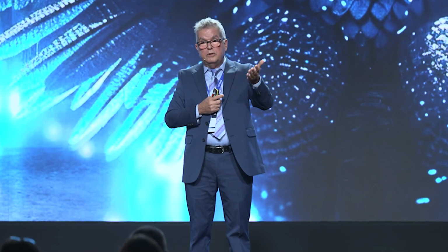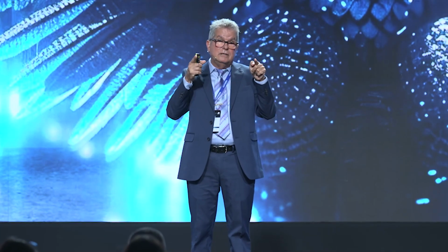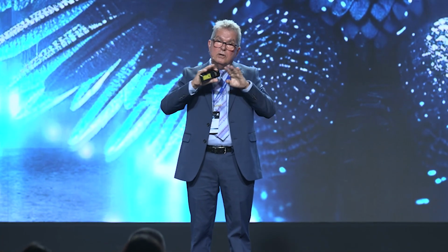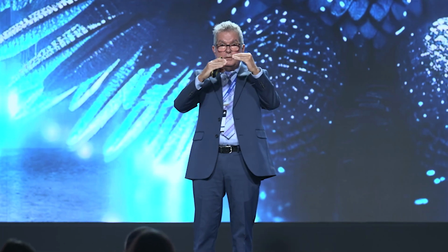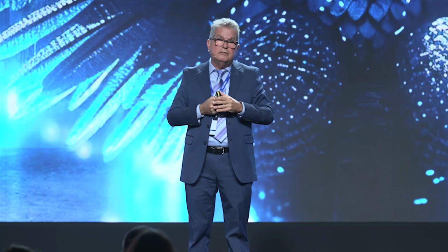The problem in these dredging sediments is that the kaolinite content is a little bit low. We're seeing this is between 30 to 35% kaolinitic clays, but also you have 2-to-1 clays in there. You have illite, montmorillonite, and what we're seeing is that if the total amount of clay minerals is up to 50%, you are in a very good shape, even if you have 25% kaolinite content. I mean, you have to work with the calcination temperature, probably elevate it a little bit more to dehydrate the 2-to-1 clays, but yeah, this is a good case.